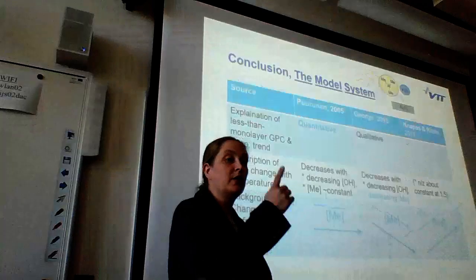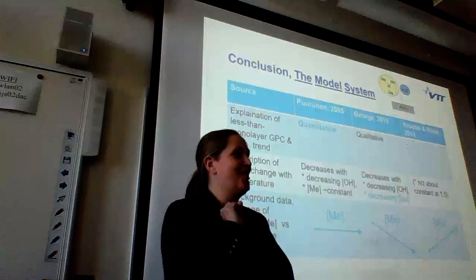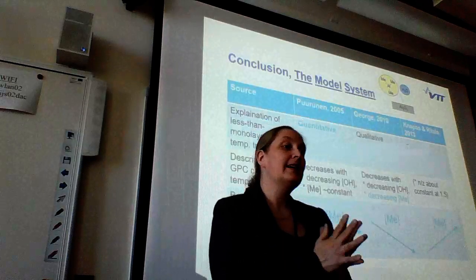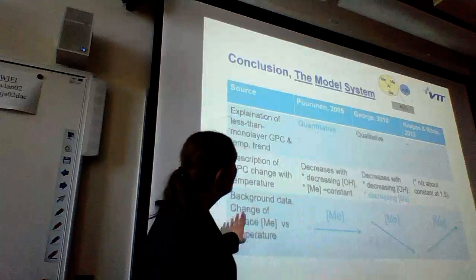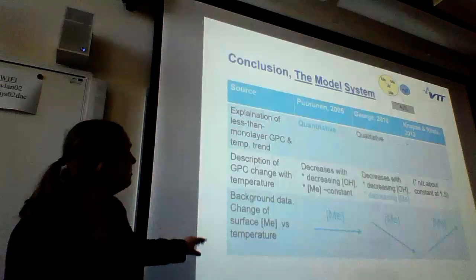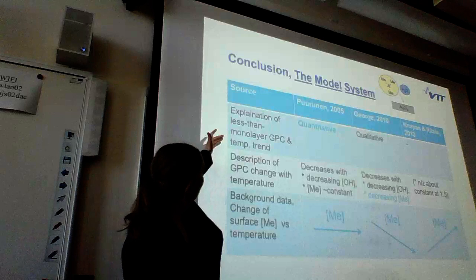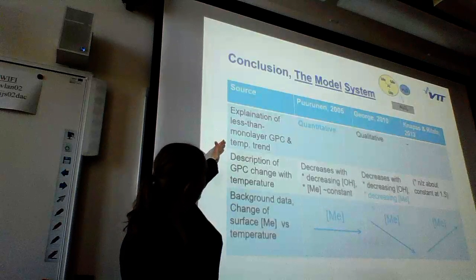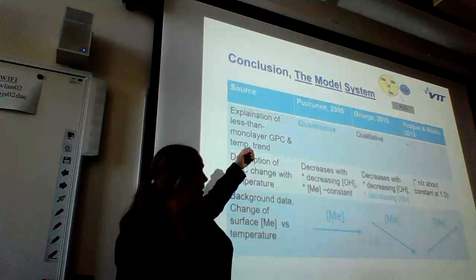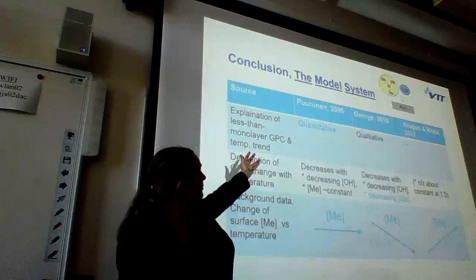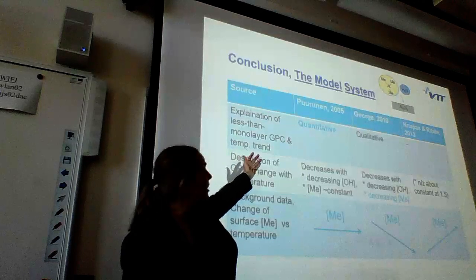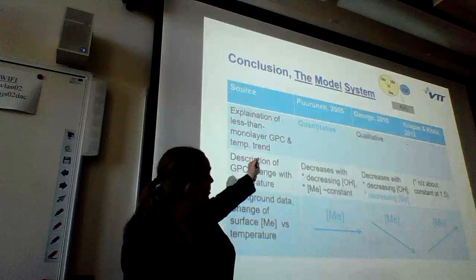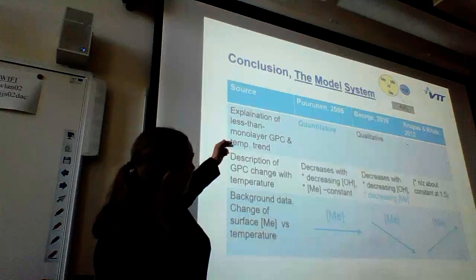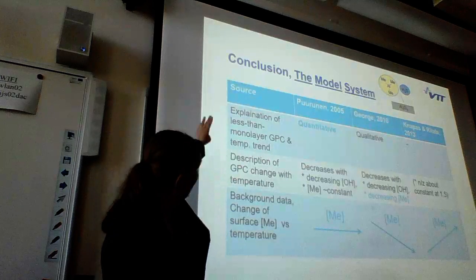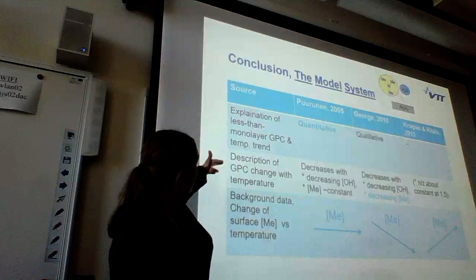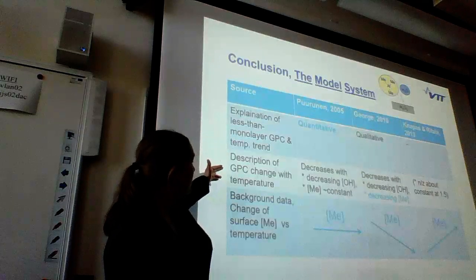Now I skip, as planned, over the other explanations, but this is the conclusion slide from last summer. So explaining the less than monolayer growth per cycle and the temperature trend, I claim at least that I have a quantitative explanation for that. In the George review there is a qualitative explanation. Knapas and Ritala didn't try to give any explanation for this description of the growth per cycle change with temperature.